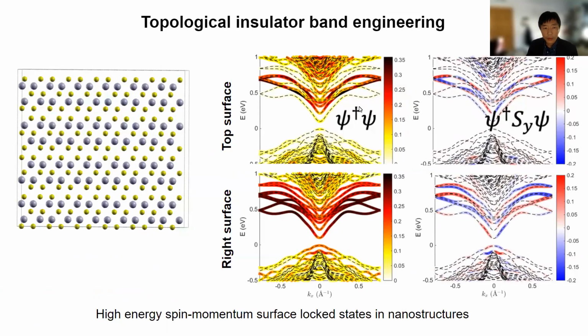Okay, so when we first looked at spin-orbit torque, one of the first materials we looked at was the topological insulator. In this work, we study the Rashba-Edelstein effect. Here I have a topological insulator, and we ask whether we can engineer the Rashba-Edelstein effect by going to nano dimensions. In this case we look at bismuth selenide, and specifically a nanowire of bismuth selenide. What you see here is a cross section of that nanowire.